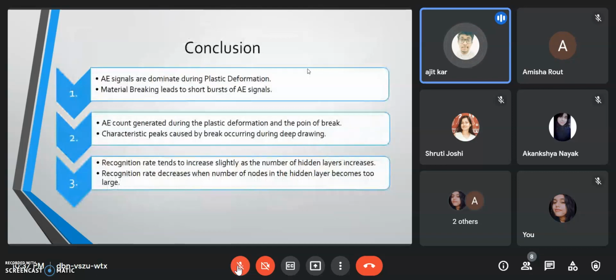So machine learning, which is a multi-layered neural network, is implemented to recognize the forming state during deep drawing processes. It is a new processing method which was proposed by using the count rate of AE. AE measurements during the tensile test show that continuous AE signals are dominant during plastic deformation and there are short bursts of AE signals at break. There is a difference between the AE count generated during the plastic deformation and at the point of break. AE count in the deep drawing showed that there are peaks caused by breaks occurring during deep drawing. Therefore, it is possible to recognize the forming state during the deep drawing by measuring the AE count.